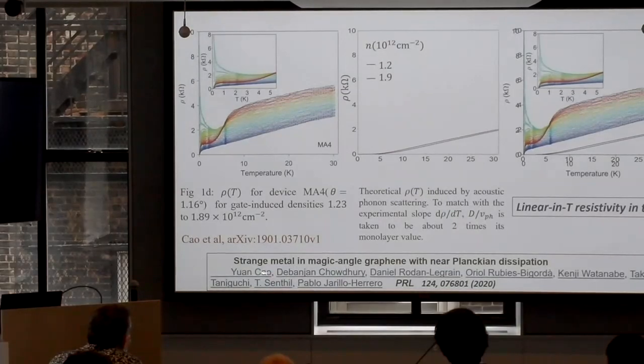And I think that I'm going to come back to that. This issue is not completely resolved. Meaning, since I'm going to talk about superconductivity, we wrote a recent paper where we looked at this question very carefully because of some new data Efetov has published, very careful temperature dependent data. So we got the data from them and used actual numbers and did our electron-phonon calculation very carefully. And what I'm confident is that all the linearity they see above 10 Kelvin is coming from electron-phonon interaction.